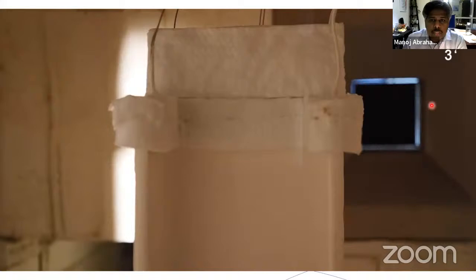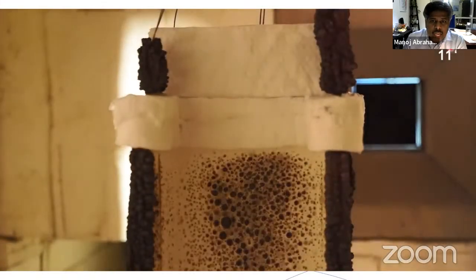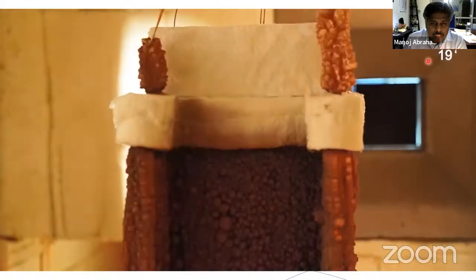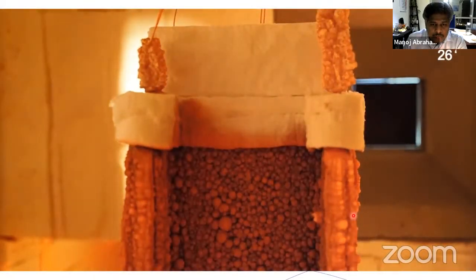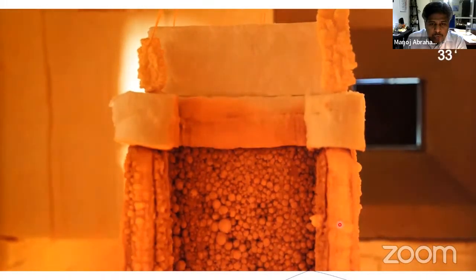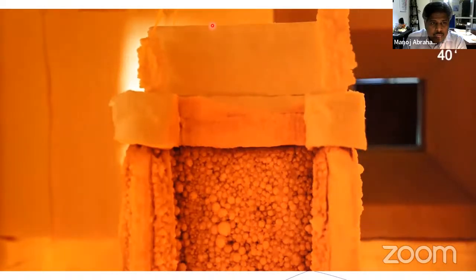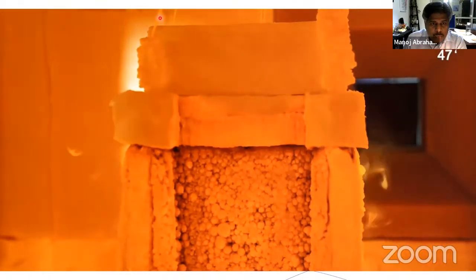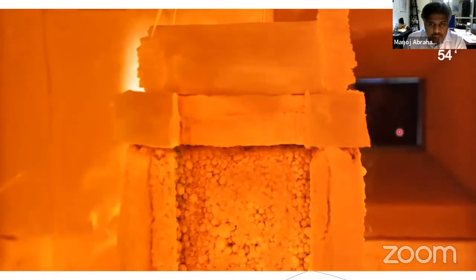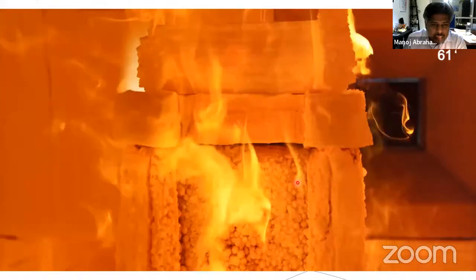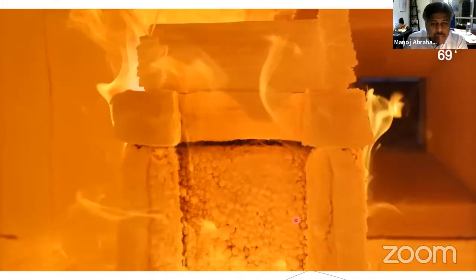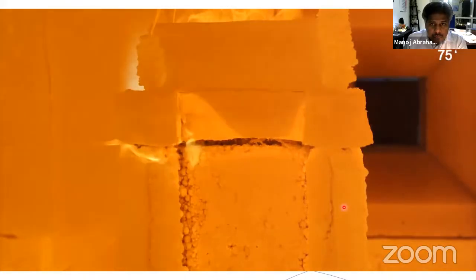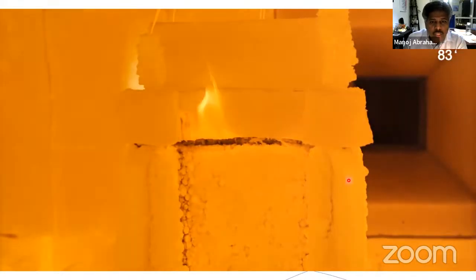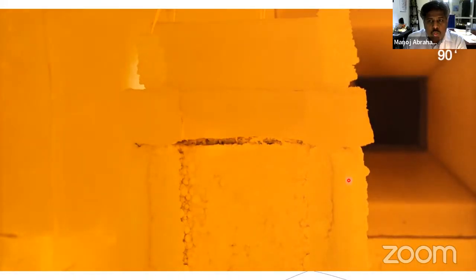This video is taken in our Barcelona lab. You will see an I section connected to thermocouples here, and you see this is the air temperature, the ambient temperature in the oven, and you can see the coating here is expanding, and we are measuring the internal steel temperature here using this thermocouple. And you can see that even though the temperature reaches even 900 degrees centigrade, the structure still stands. It has not collapsed. And you see that the coating has fully expanded. After 1000 degrees, I think we lost our camera also, right?